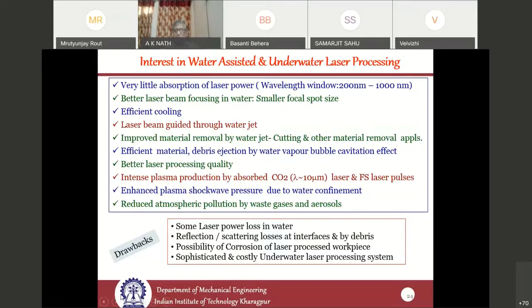There are some drawbacks. Some laser power loss in water takes place. Reflection and scattering losses at the interface and by debris could take place. Possibility of corrosion of the laser processed workpiece could take place. Sophisticated and costly underwater laser processing system compared to gas assisted system.